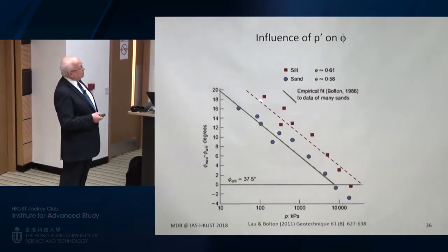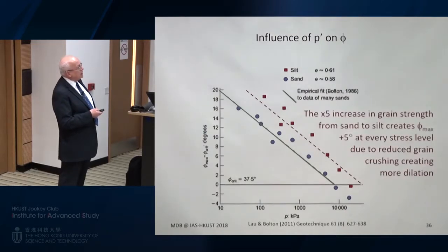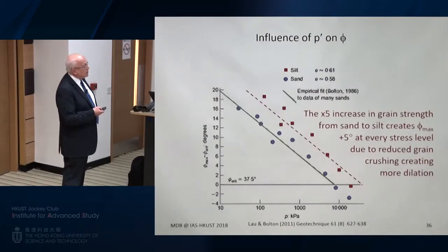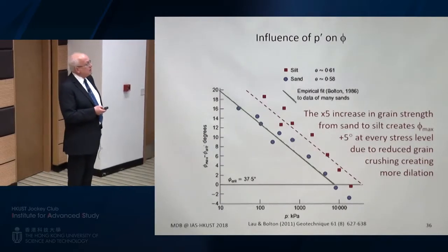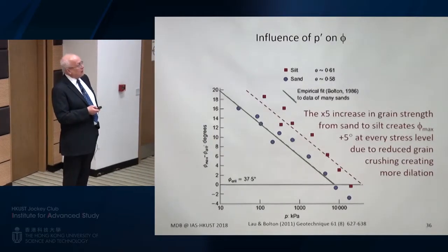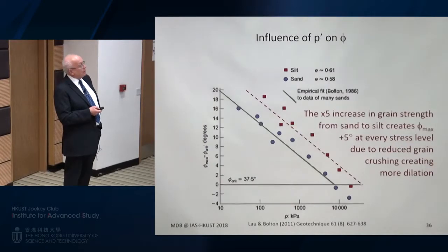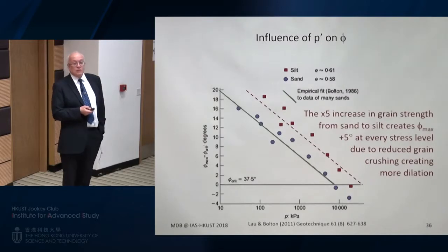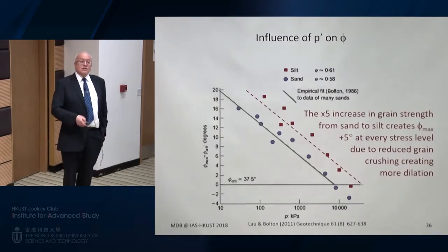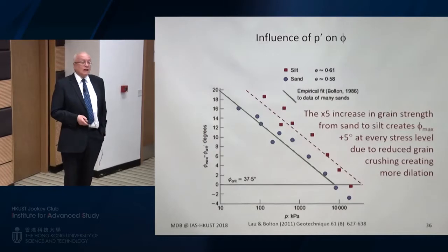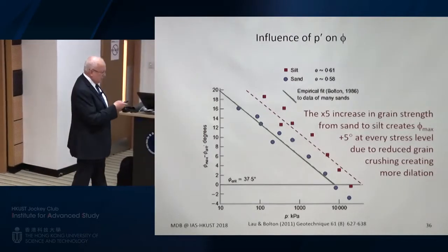So, as I was saying, you could either regard the silt as 5 degrees stronger or as 5 times stronger. If you look at the horizontal axis, you've got to multiply p dashed by 5 to get the same result. If you look at the vertical axis, you've got to add 5 degrees. So it's the same relationship between strength and dilatancy, and you can express it either way.